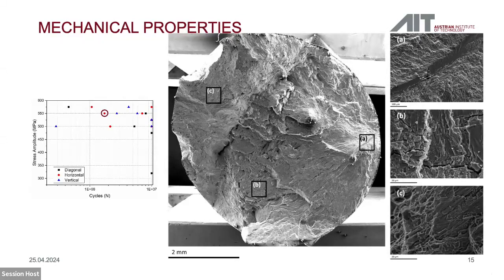So this is quite surprising at first, but if you look in detail, you can see that the pore that initiated the crack was located at a prior beta grain boundary. And this is something that can happen, shouldn't, but in statistics, it can, of course, and this is why this sample failed earlier than the other.